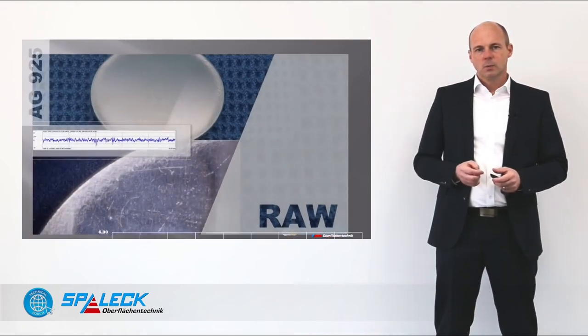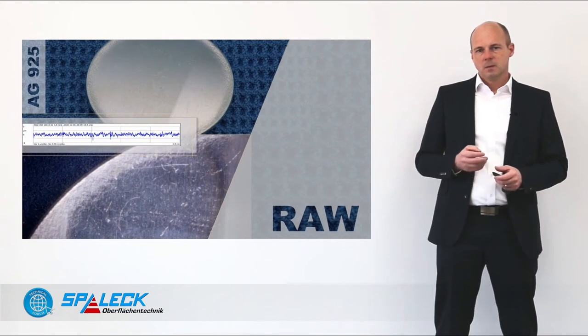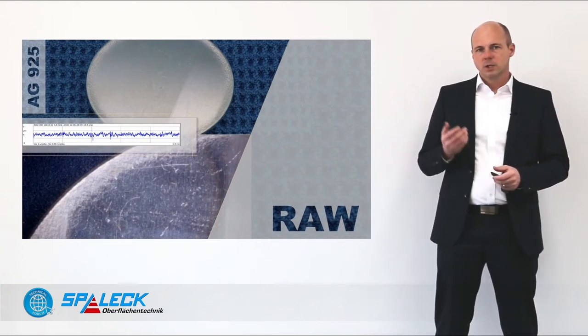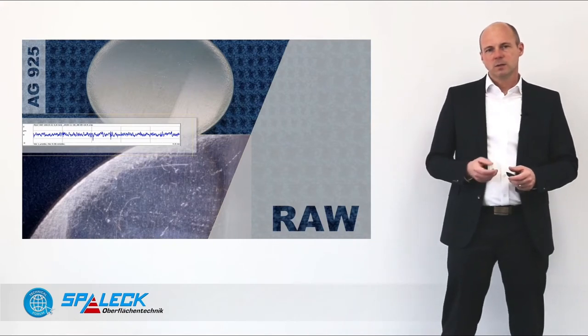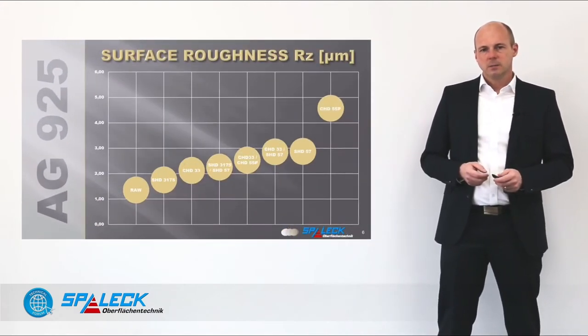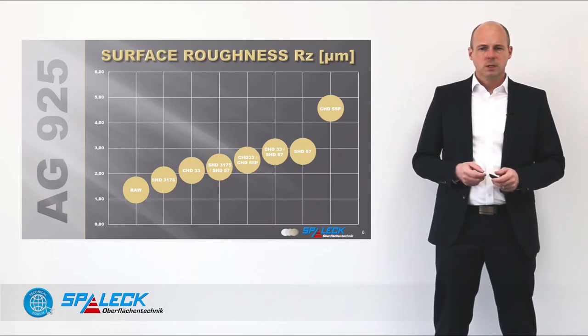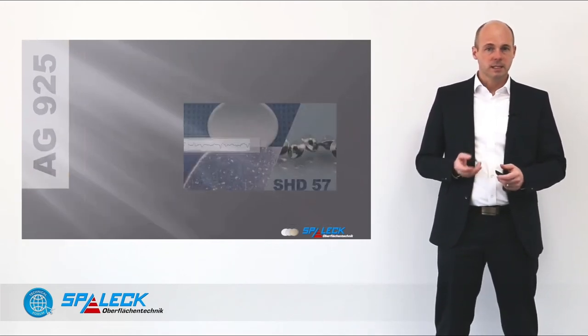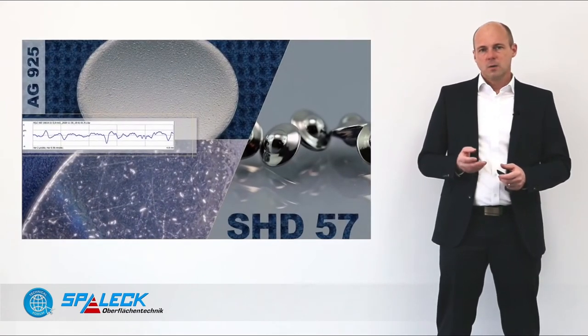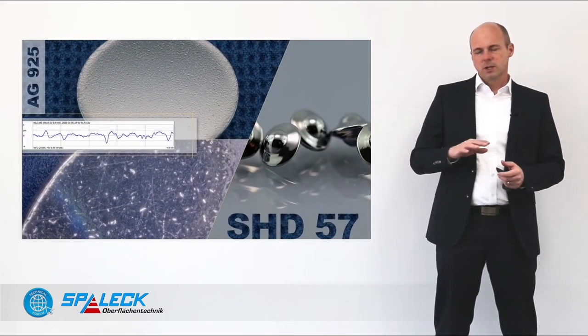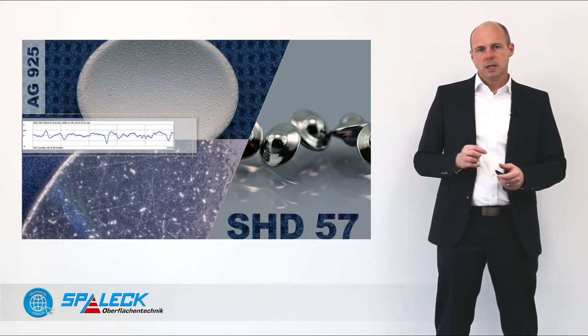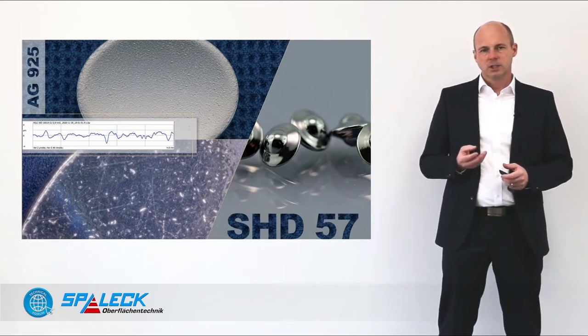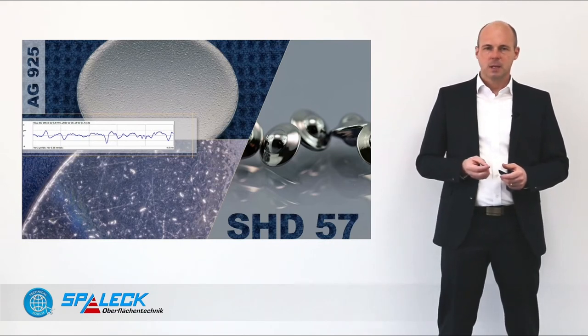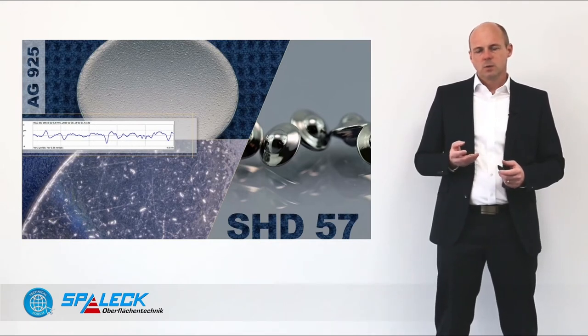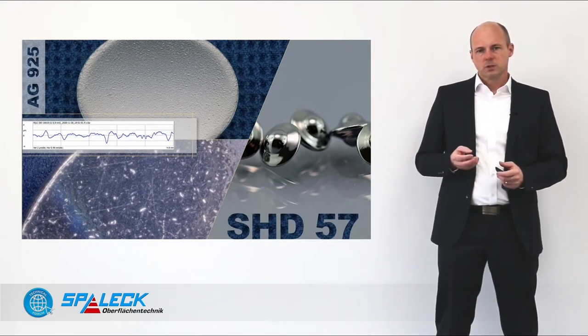As mentioned, we want to eliminate especially the rolling marks, which are visible here on the photo and also on the microscope, and that can be generated very efficiently by the stainless steel satellites, which are removing the structure from the rolling marks and are also capable of hiding little scratches from the surface. Finally, you create kind of an orange peel, which is also promoting the material flow during the striking process.